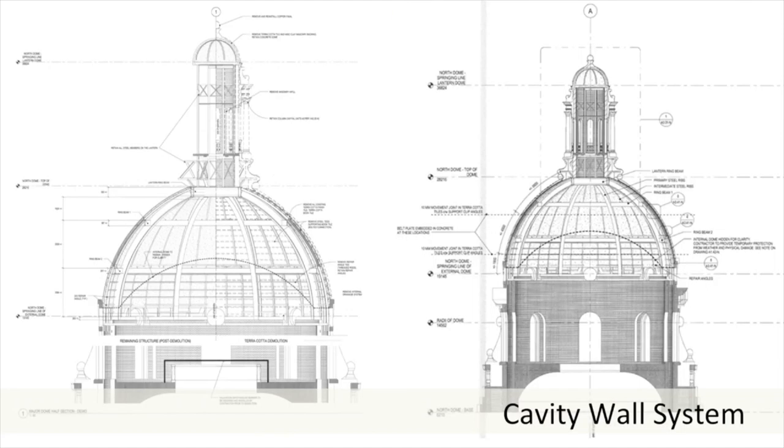You're looking at two diagrams — the old system and the new system. The old system was basically fill it solid with grout up against a backup terracotta speed tile and pin it back with soft mild iron anchors. That held up for about 100 years — it had gone through several repairs, but it's amazing it withstood 100 years with just that older installation system. The new dome was put back historically correct but hung as a rain screen system with all stainless steel anchors.